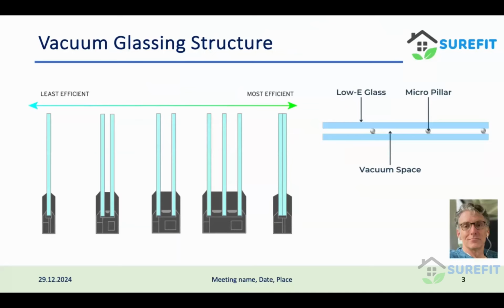Windows came from single panes, and they started going to double panes for more insulation. Then double panes with a larger gap insulated with gases like argon. And then to get really effective insulation, they started going to triple pane windows. But they became thicker and thicker. What we offer here is two pieces of glass very close together with a vacuum in between. They're so close together they look like a single piece. Because of the vacuum, they would collapse if they didn't have supports, so there are actually little stainless steel balls or pillars in between to keep the glass from collapsing on each other.